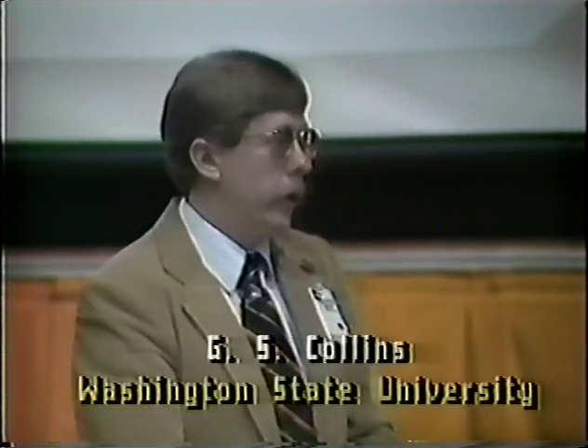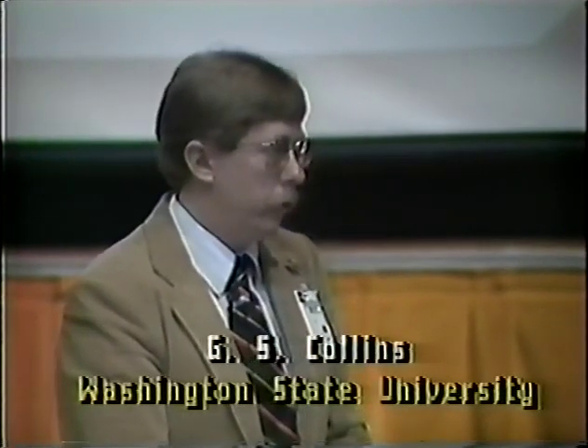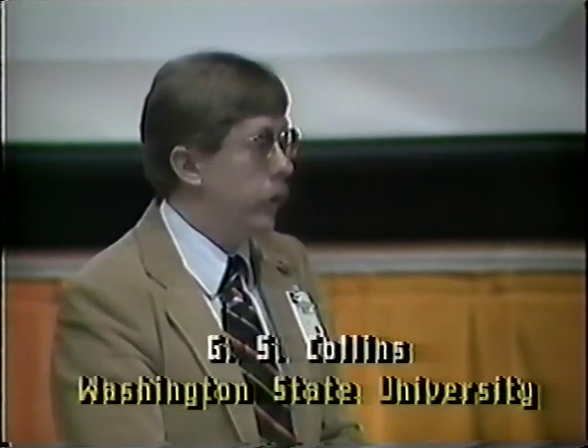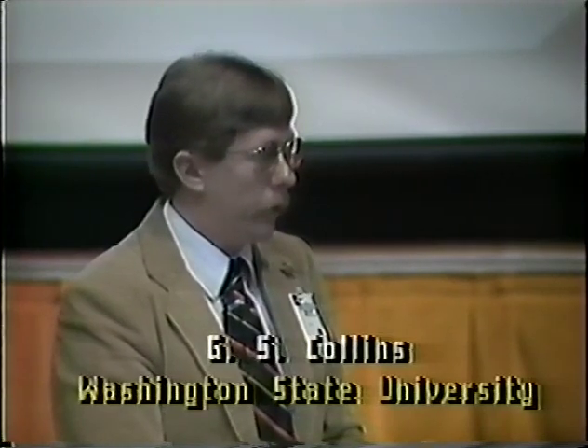deposition goes, we're undertaking a neutron activation analysis to detect quantitatively the amount of lithium which has been deposited on one of the samples. Lithium-7 goes to lithium-8, which has a 0.8-second half-life, but if you use a rabbit system, you can do neutron activation analysis. I think your technique is very interesting, very new and exciting.